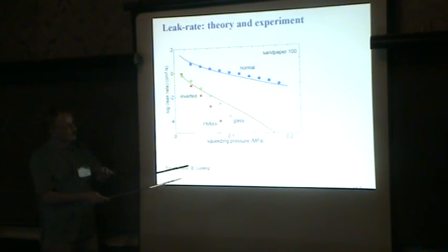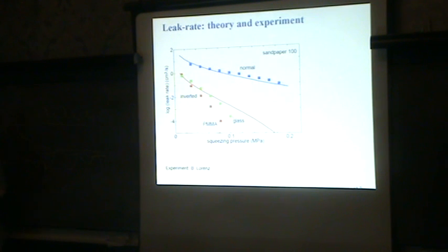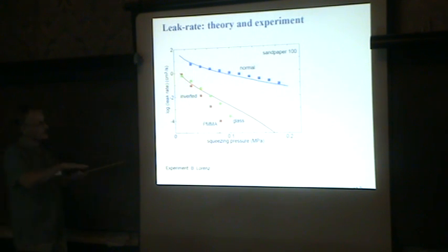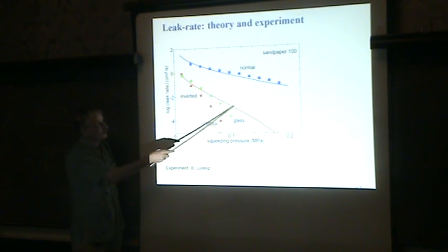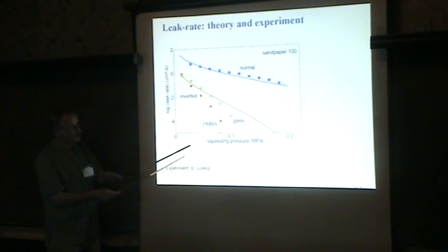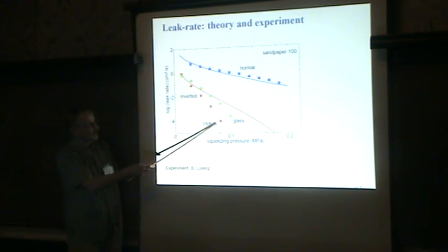Because these tops of the inverted surface are very smooth, they can become in adhesive contact with the substrate, and they will pull the surfaces into closer contact. So the leakage rate will drop below the value predicted by the theory. This effect is larger on PMMA than on glass, because the attraction is stronger with a PMMA surface.